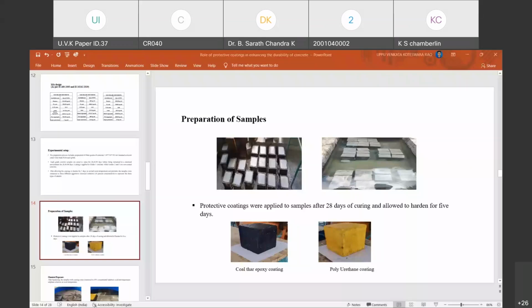And these are the sulfate solutions like MgSO4, and I have considered another solution, H2SO4, which is an acid solution. Here I considered M20 grade concrete with protective coatings, two protective coatings, coat 1 and coat 2, for 28 days exposure, 56 days exposure, and 90 days exposure. Here we can observe there is less variation of strength for both protective coatings. Compared to coat 1, coat 2 is more resistant, which means there is less strength loss in coat 2, which is a coal tar epoxy coating.